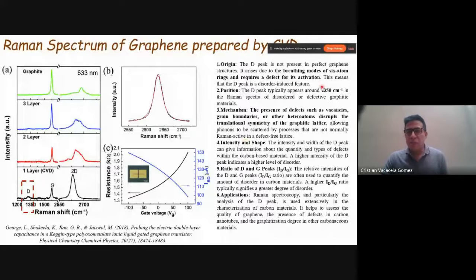Also, this is the position: more or less, the D band is detected at 1,350 centimeters to the power minus 1. We need a deeper analysis of the Raman spectra, but as a first approximation, we can attribute the presence of the D band to defects such as vacancies, grain boundaries, or other types of defects. And you can read more details about this band.